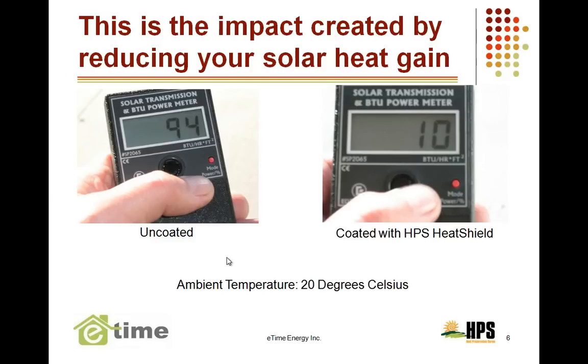The BTUs are basically measured by how much is penetrating into the envelope per hour and per square foot. So this is contributing 94 units on the uncoated window, which, as you saw before, is 21 degrees. On the second coated window, it's dropped to 10. Now, that's an 80 to 90% drop with respect to its ability to block what's heating the interior of the envelope. This is very significant because that's what your dollars and cents are paying for, is to keep the heat in the envelope in the winter and trying to keep the cooling in during the summer.